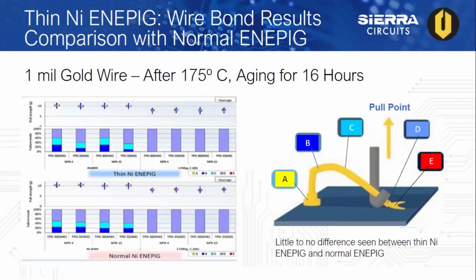These comparisons were made on different Uyemura palladium and electroless nickel products. The overall performance between thin nickel deposit and normal nickel deposit in the ENEPIG are very similar with no significant differences. The failure modes are also very similar between both finishes.